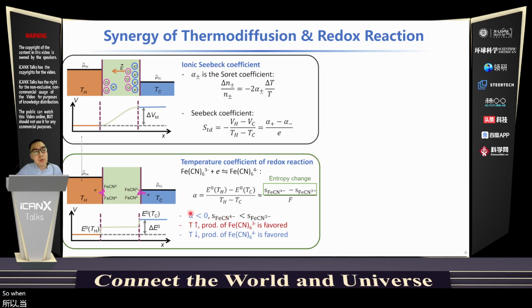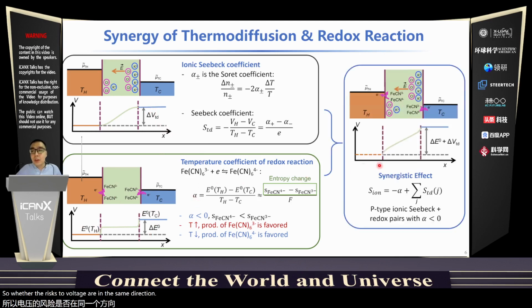When temperature rises, entropy favors the production of the higher entropy state. So on the hot side, we will have oxidation, but on the cold side, the opposite reaction happens. This chemical reaction shift also generates a voltage. So when these two voltages are in the same direction, you can actually achieve a boost when the electrolyte contains both redox pairs and ion providers for thermal diffusion.